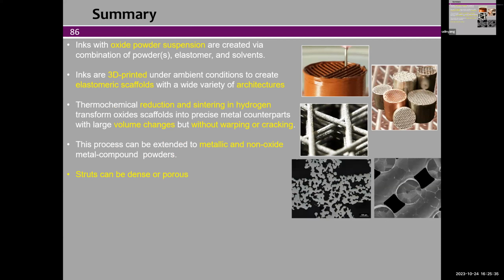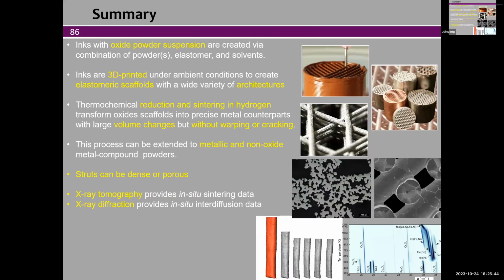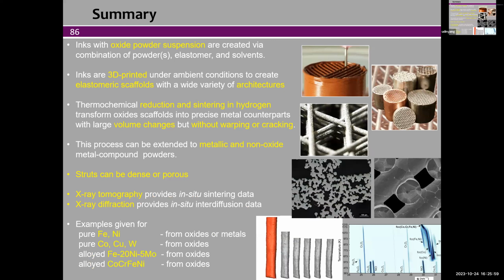The structure can be dense, like in the tungsten, or porous, like in that nickel example, if we want to get additional porosity. And then we did X-ray tomography to get the outside shape as a function of temperature, and X-ray diffraction, which tells us the sequence of phases that happens during that cascading reduction from oxide to metal and interdiffusion to form alloys.